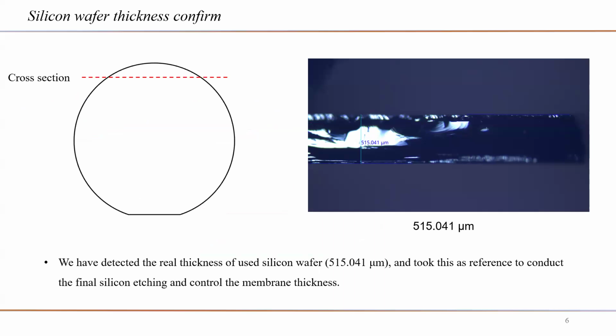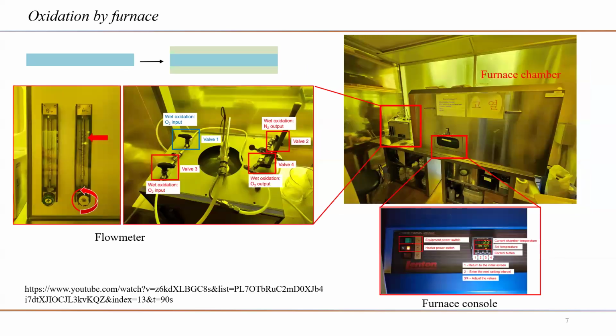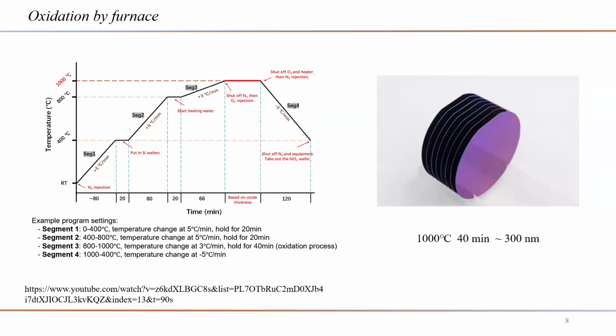This is the silicon wafer that we use. We measured the wafer thickness at around 515.041 micrometers and took this as a reference to conduct the final silicon etching and control the membrane thickness in the fabrication process. After wafer cleaning, we use the furnace equipment to do the first oxidation process. We completed the wafer oxidation step using the parameters of 1000 degrees Celsius for 40 minutes to obtain an oxide layer approximately 300 nanometers thick.